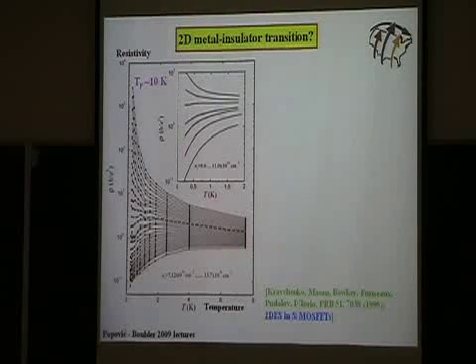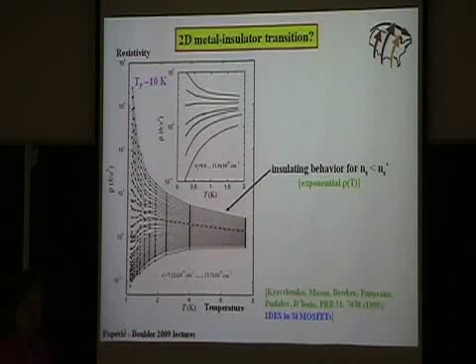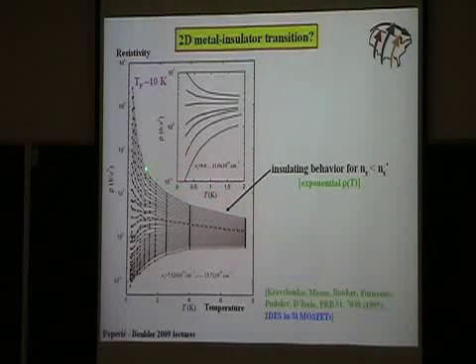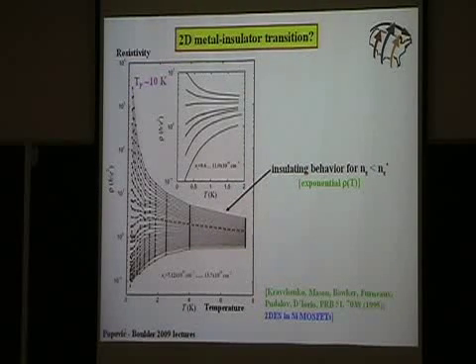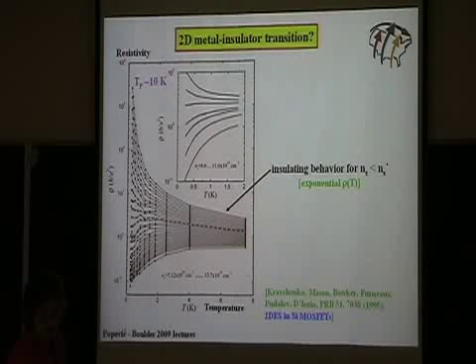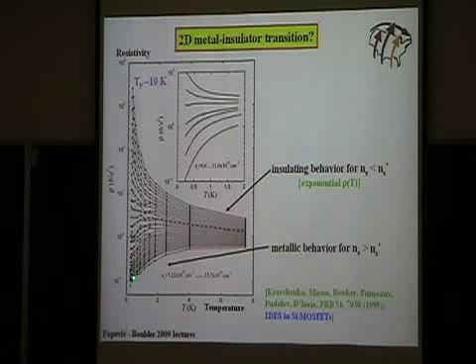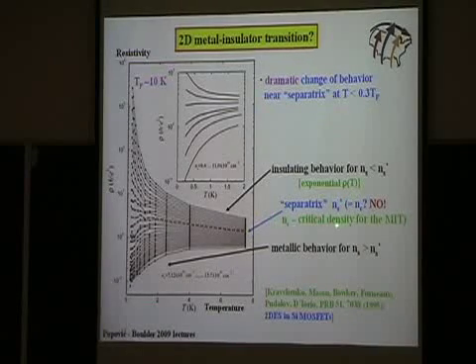Now I come again to the question of the 2D metal-insulator transition. What do we see if we measure resistivity as a function of temperature in this silicon MOSFET? These different curves correspond to data for different electron densities, starting from the low density. You can see that at low densities, as temperature goes down to 0, resistivity increases exponentially. So it exhibits insulating behavior because in the zero temperature limit it will diverge, the conductivity will be 0. However, at higher densities, which is here, the resistivity actually drops as temperature goes down. So this is metallic behavior, and it's hard to extrapolate to 0 in this case, but if you did, you would end up with a finite value of conductivity. And then there is a density which separates these two types of behaviors, which some people call the separatrix for that reason.